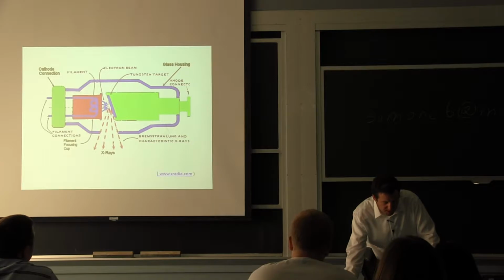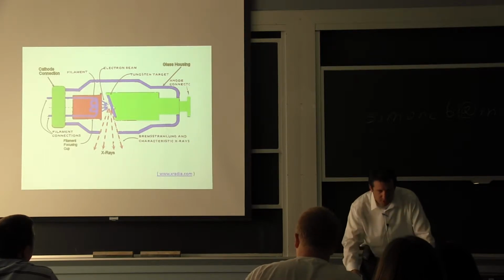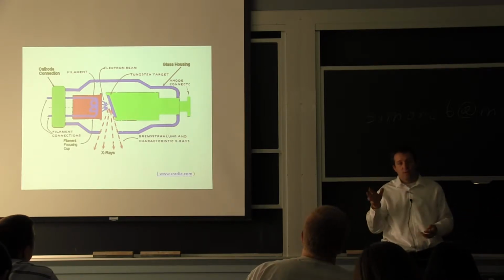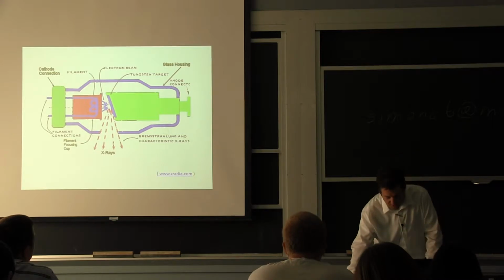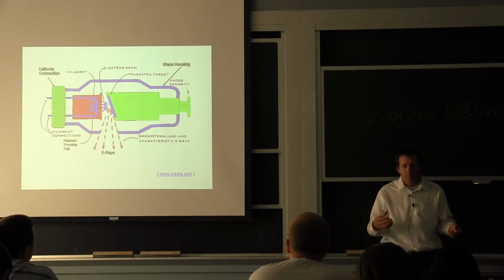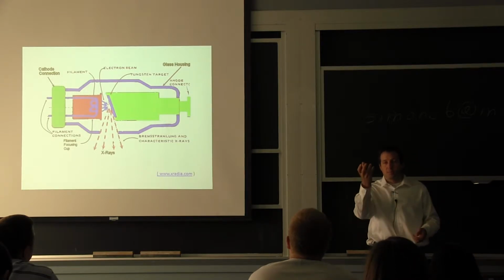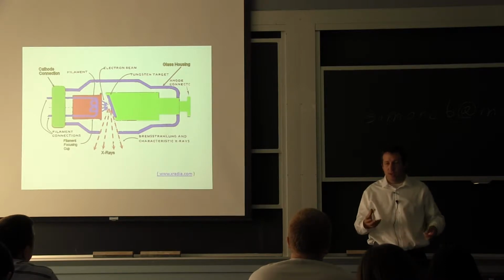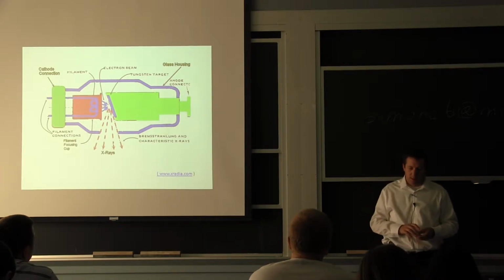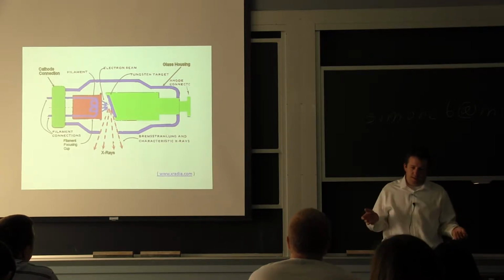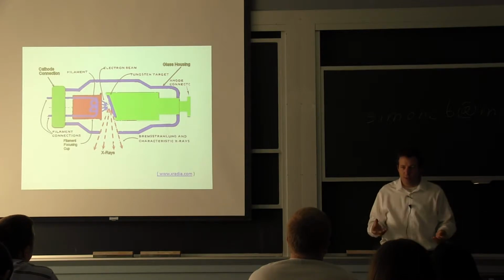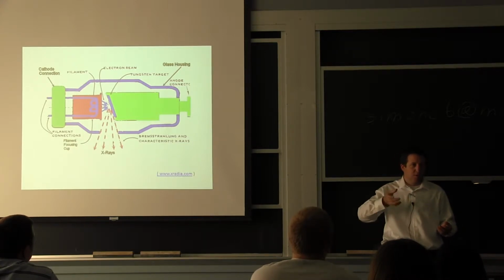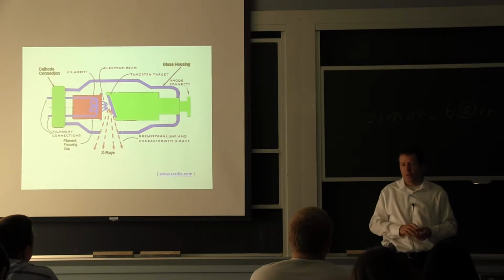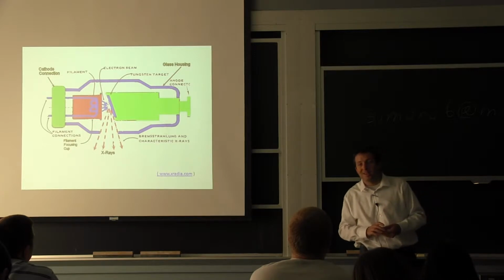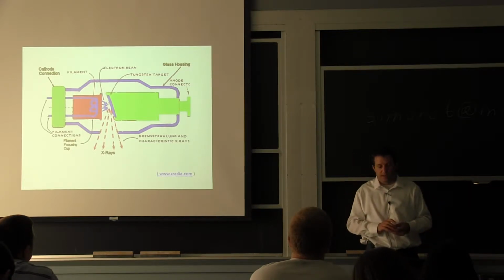So in terms of design, what you need is something that is this high temperature on the surface, because you know it will heat up. The beam is so strong, there's no way to avoid it. But then behind what you see as the green is essentially a copper block that has internal cooling to try to drag the heat generated from the electrons hitting the tungsten. So this whole system, if you're running it in steady state, you keep providing electrons, you keep generating heat, that's great. But when you start turning it on and off, the surface moves from tension to compression every single time at very high frequency. And that's why they only had a few months' worth of life on these sources that were worth a lot of money, and that was not acceptable.